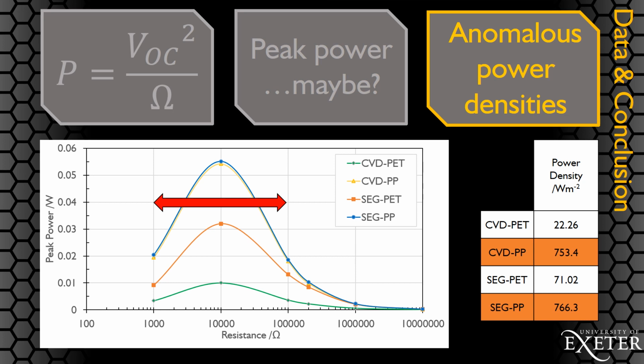We attempted to rank the electrical output of the TENGs through power density, but when comparing values to a review paper, our results appear roughly 2 orders of magnitude larger than the one stated. The PP fibers show larger readings as only one fiber was placed across the TENG's operational area, despite the entire area still being measured. Reports exist of power densities in the several hundreds of watts per meter squared, so it's possible that our devices were better performing than expected, but also likely a systematic error that was present and could not be resolved.